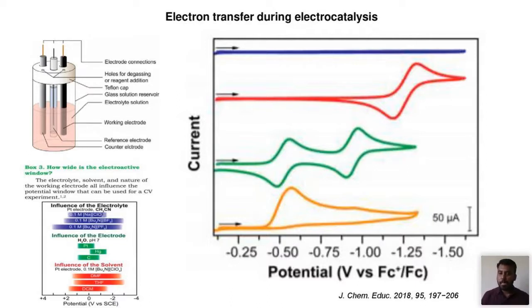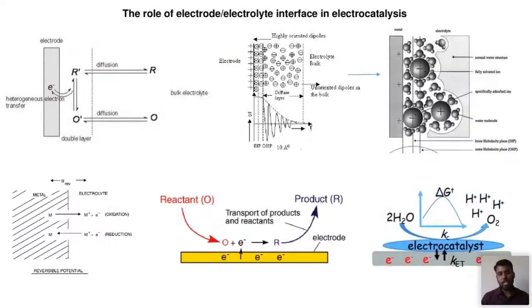The peak in the reduction potential region is called the reduction peak, and the peak in the oxidation potential region is called the oxidation peak. This is called a reversible redox process, and it will give you information about how many electrons are transferred. For example, the blue curve is recorded in a nitrogen environment, whereas this other curve is recorded in an oxygen environment. It undergoes a one electron transfer process, whereas here a 2 electron transfer process is happening. So multiple electron transfer processes can happen, and based on the number of electrons transferred, your product will vary.